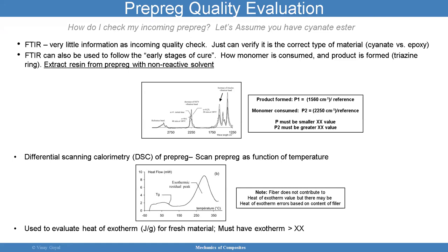FTIR is Fourier transform infrared spectroscopy, okay? That allows us to understand how strong the interactions are within the composite. FTIR provides very little information as an incoming quality check. With FTIR, you can check whether the material you received is the correct one. If you purchased, say, a cyanate ester but received epoxy instead, an FTIR can at least tell you that it's cyanate ester, not epoxy, so I must have gotten the wrong raw material. An FTIR can also be used to follow the early stages of cure.